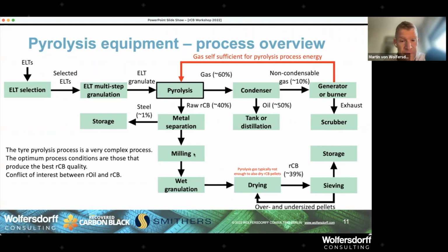Then you need to mill the recovered carbon black, because at that point it has a very large particle size distribution, which is between microns and millimeters. There could even be chunks of centimeters. We go into a wet granulation. Now, you might ask, why do we need the granulation? Why do we agglomerate again where we have just milled? That is in order to increase the bulk density. And the difference could be whether you send one truck or two trucks to the customer. So if you have a very fluffy material with a very low density, then you need to send two trucks. And with the agglomerated pelleted material, you would only have to send one truck.